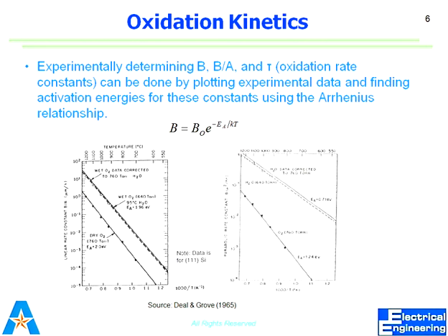So activation energy at different temperature and at different orientation, depending upon whether you are using 111 or 100, this activation energy would be different. But EA, the activation energy, would be given in the table, and B naught would be given to you. If you want to find out what my reaction rate B is at a specific temperature, you put that T value and you find out B. But usually we always get that from the table.